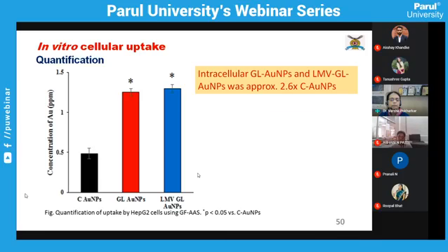The in vitro cellular uptake by CLSM gives us the qualitative aspect. Quantification further was done by carrying out studies using GFAAS, that is graphite furnace atomic absorption spectroscopy, where we can quantify the amount of gold. And we could see here that the intracellular uptake of the GL gold nanoparticles and lamivudine gold nanoparticles was 2.6 times that of the citrate reduced gold nanoparticle. So this again clearly established that the strategy was successful in targeting the nanoparticles to the hepatocytes.